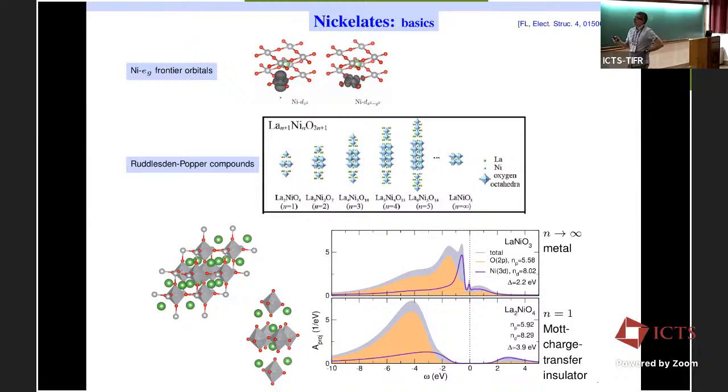So the dominant orbitals are then from the 3d shell, usually these two degenerate orbitals of eg kind. So it's dz² and x²−y². And those two orbitals really play the main game in this physics. So this is important to know. That's usually a twofold orbital sector that is most relevant.